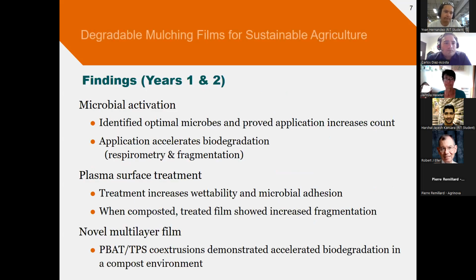So what did we find? The microbial activation. We identified optimal species, optimal microbes, and proved that the application increased the count. So it's easy to say the concept, but to go in the lab and actually demonstrate it is no easy task. And Harshal did some very interesting work on this. So we demonstrated that, and then we also demonstrate that the application accelerates the biodegradation, both the fragmentation, the physical degradation, and the conversion of the organic matter in the film to CO2. That's the respirometry.